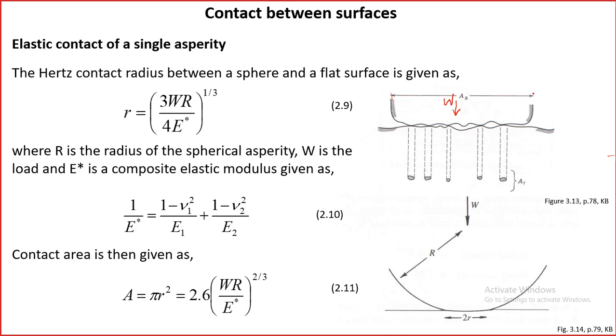The actual contact area is only at these points, and these points are known as asperities. They are some projections on the surface. So these are asperities. And from the profile study, we have understood that the slope of these asperities, the angle between the surface and the asperity, is quite low. It will be in the range of 10 degrees, if we plot the profile in the same scale in the length direction and the height direction. Therefore, these asperities can be modeled as a sphere on a flat surface. So this is how we can proceed to find out the contact area.